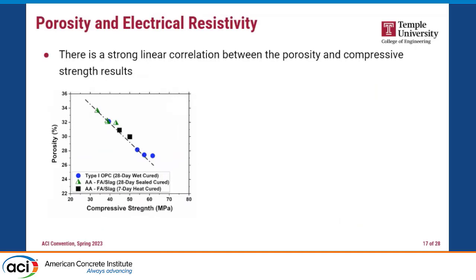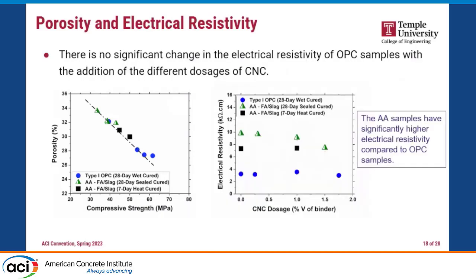We looked at the porosity of this system. There's a strong linear relationship between the compressive strength and porosity. For the electrical resistivity, we saw some abnormalities, and we think this is mainly due to the leaching of the alkalis from the unreacted phases in the system. That's why we are seeing a higher electrical resistivity for alkali activated versus the OPC.